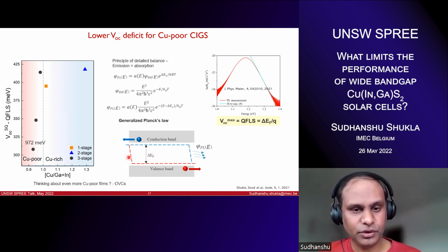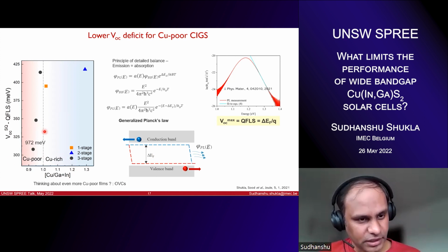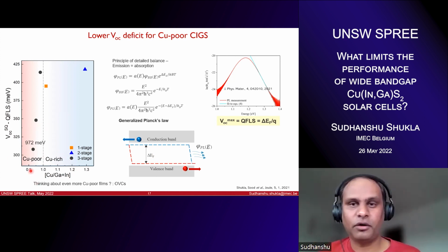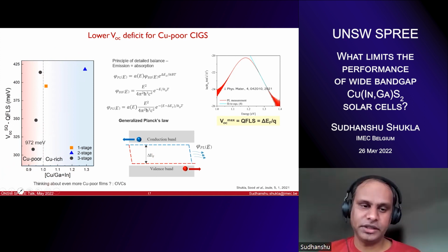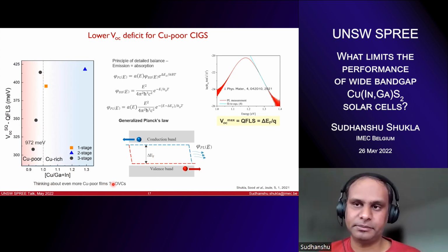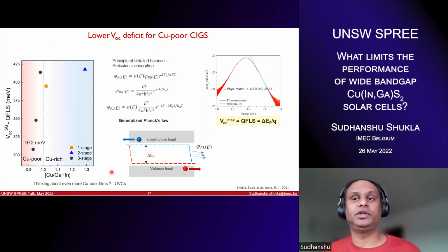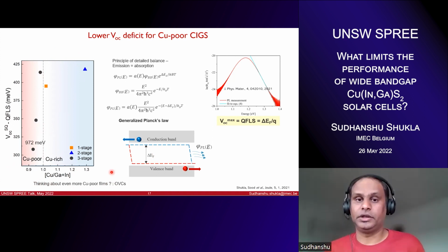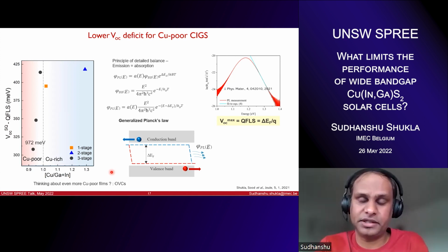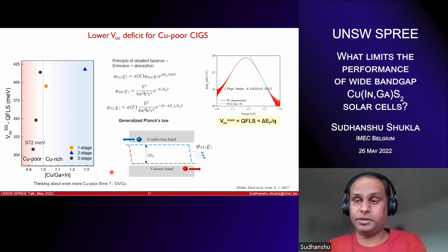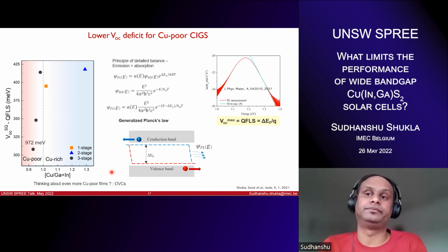Now, one last thing before you ask me: did you go even below this CGI of 0.93? Obviously, when we were seeing the improvement, we should have gone, right? If you're thinking about even more copper poor films, think about ordered vacancy compounds and CIGSe absorbers. What happens when you make them highly copper poor? You do get the onset of ordered vacancy compounds, which actually helps in passivating interface recombination. But whether these OVCs exist in the case of sulfides, we don't know.